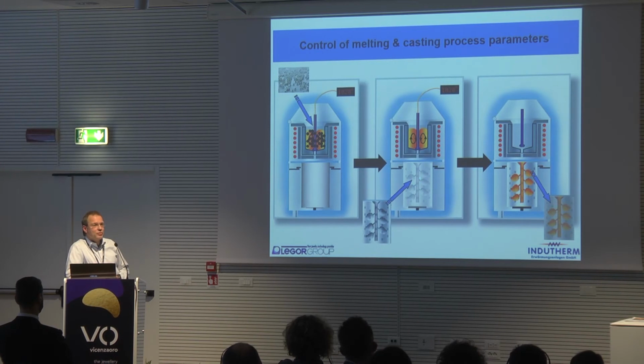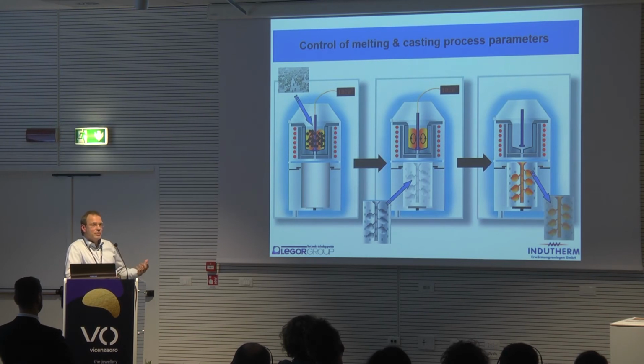When do we load the flask into the machine? When we take it from the furnace, it's full of air. We should put it into the machine early enough to allow the atmosphere to be cleaned, to really take out all the air from the mold. If this is done early enough, like 1 or 2 minutes before pouring, then this is usually sufficient. Casters are sometimes afraid of the drop in temperature by waiting so long with the flask in the machine, but we can tell by many measurements on the flasks that this effect is really minimal, and the benefit instead is that we have a clean atmosphere in the flask before we pour.